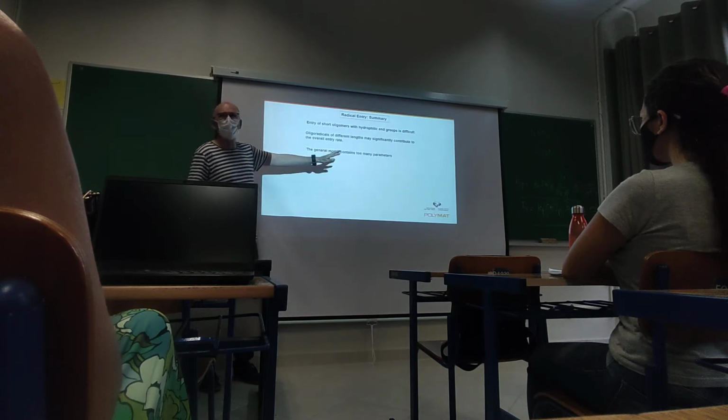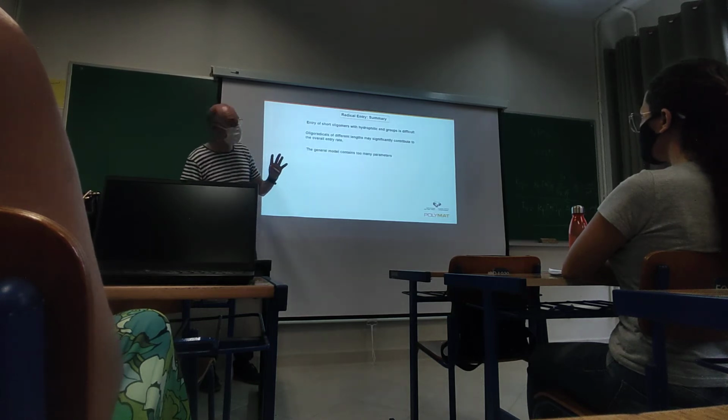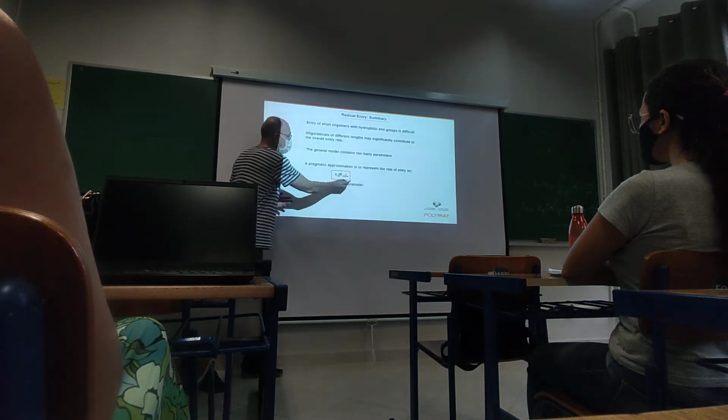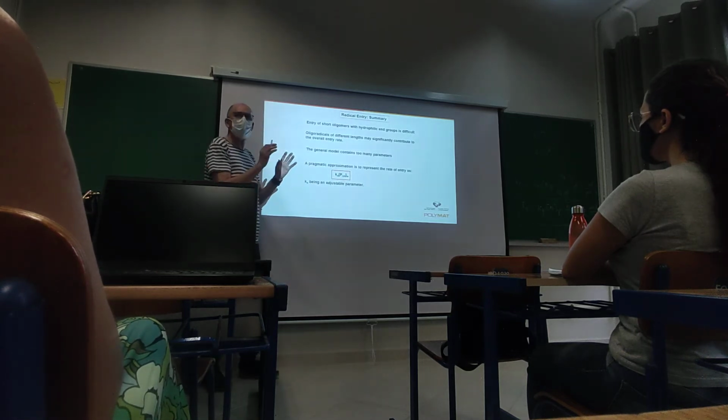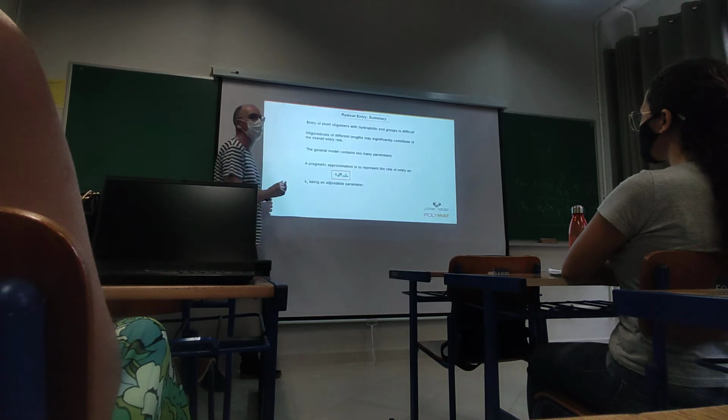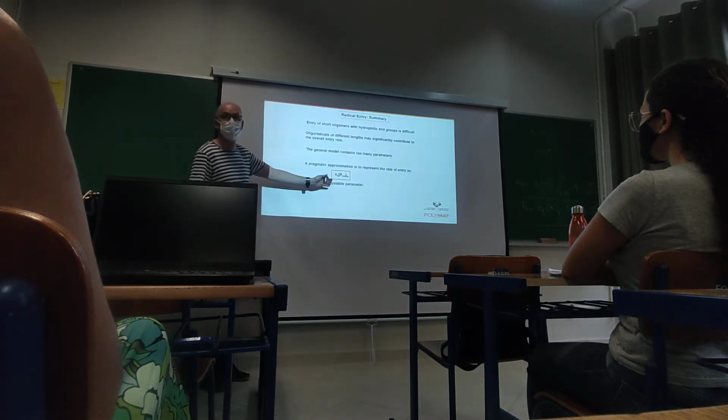And the general model is too complicated. So normally, what we do when modeling entry is to assume that the entry rate is an absorption coefficient without dependence on the length multiplied by the total radical concentration. So this is what is normally accepted, or used because it's much easier.